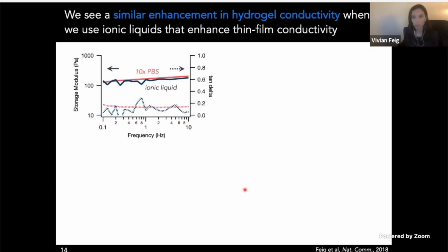And so based on this, we were really curious to see that if we formed hydrogels with one of these conductivity enhancing ionic liquids and compared it to hydrogels made with the salts in PBS, which don't have any sort of conductivity enhancing effect in films, if we could see some differences in these hydrogel states as well. And indeed, we find that in both cases, we can make materials that have very similar mechanical properties. So both still have these ultra low storage modulus values and tan delta values of less than 1.